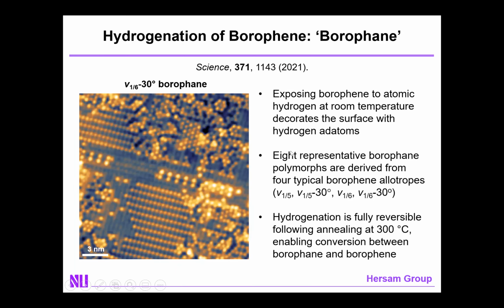Indeed, the way that we do this is that we expose borophene to atomic hydrogen at room temperature, and it begins to decorate the surface with hydrogen adatoms. Converting borophene now into hydrogenated borophene, in analogy to hydrogenated graphene being called graphane, we'll refer to this as borophane for short. But just like graphane, there are many allotropes of borophane. We've observed at least 8 distinct borophane polymorphs. And I'll note that among them, the v1/6 30 degree polymorph is the one that we can form with the highest coverage and the highest atomic purity.